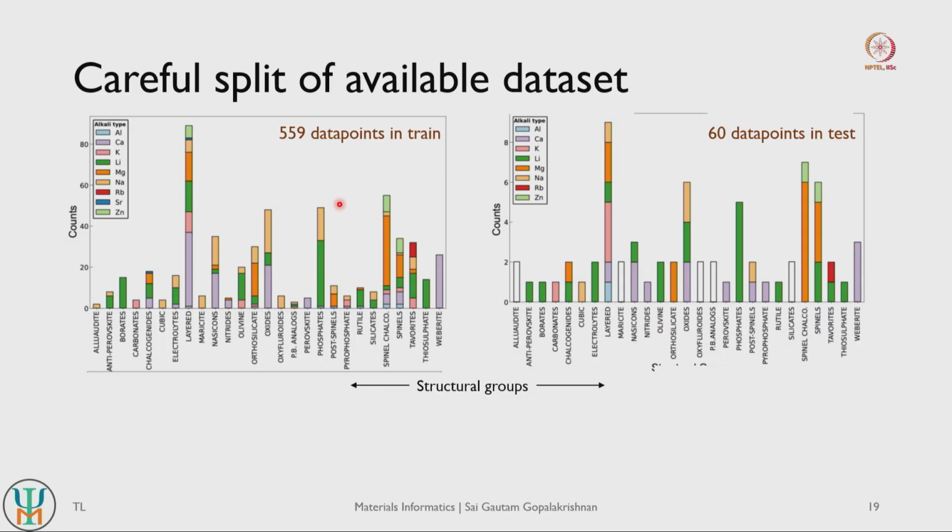So the first thing that you pretty much have to do when you have to do a fine tuning exercise is to worry about your data set, right? Our research group created a manually curated data set of calculated migration barriers. These are all obtained from density functional theory based calculations for about 620 systems. We split that carefully into training and test data sets. The split is about 90:10. So 90% of the data points go into training and 10% go into testing.